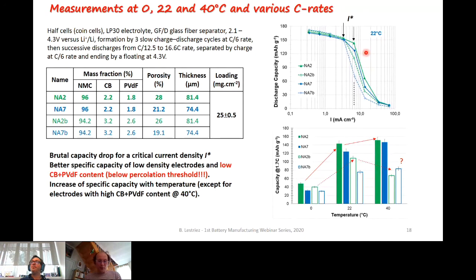This is different from what has been shown, for example, at the beginning of this week for the NMC 111 based electrode. Here we are dealing with the NMC 532 based electrode, and this active material has a higher conductivity due to a higher nickel content. So we found here that for this material, it is not necessary to have enough CB+PVdF to be above the percolation threshold. If you put CB+PVdF above the percolation threshold, in fact, you obtain lower performance. Here, the added value of the CB+PVdF is to create gateways between the NMC clusters to avoid strong contact resistance between the NMC clusters at the junction.